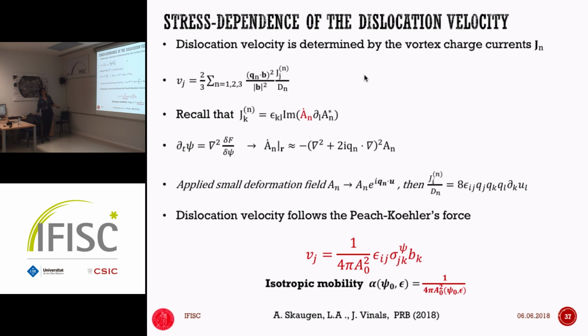And so now I'm applying a smooth force, and what we show is that within the linear regime, the current of the order parameter is directly related to the gradient of the applied field. And as a consequence, when we carry all of this machinery, the velocity field is also going to be proportional to this gradient field. And we know from what I've shown before that the gradient field is linearly related to this stress field. So basically, the velocity is directly proportional to the stress field and the Burgers vector. And this expression is precisely the Peach-Koehler force. In 3 dimensions, it's a little bit more complicated, but in 2 dimensions, this is the expression.